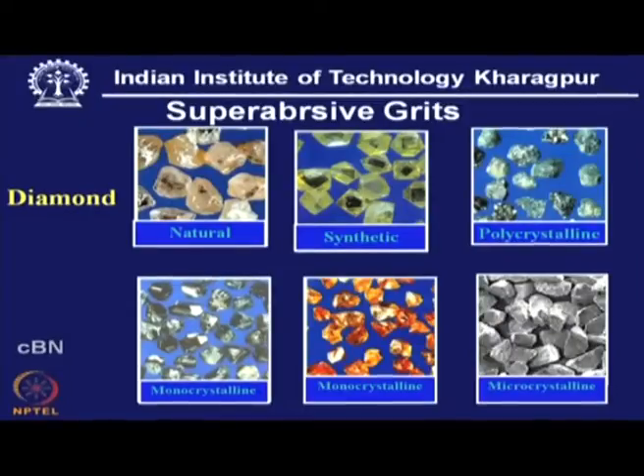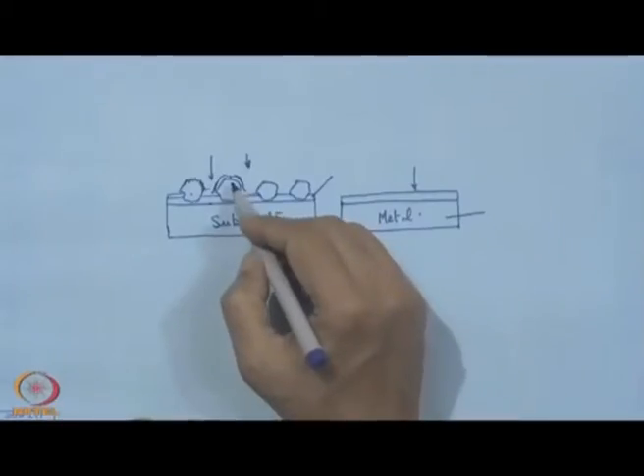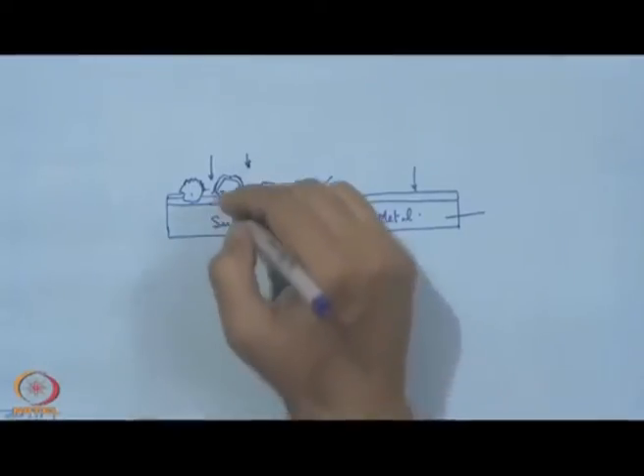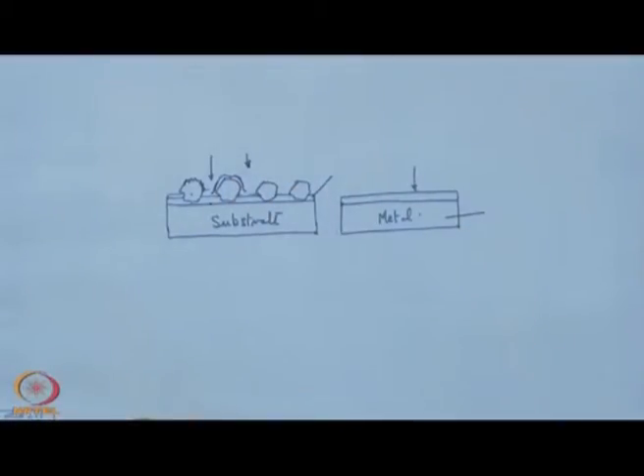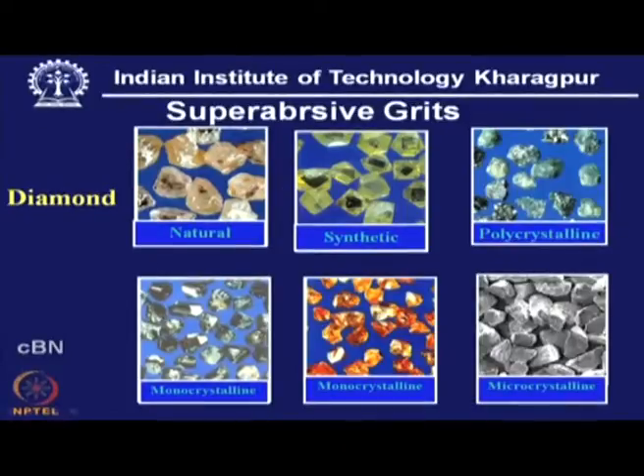However, the surface is smooth, as we see, it is a perfectly grown crystal. One thing we can see here is that it is a mechanical anchorage. Mechanical anchorage means surface roughness plays a key role in augmenting the mechanical anchorage, and this becomes automatic when we have a multifaceted appearance, but that is not possible here because it is a well grown crystal with well defined crystallographic planes.